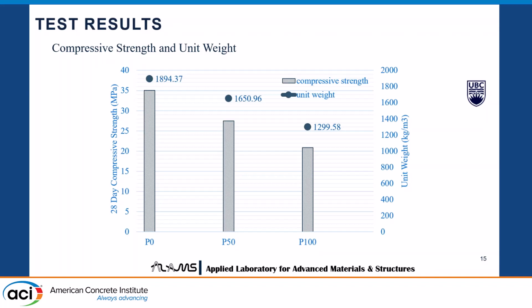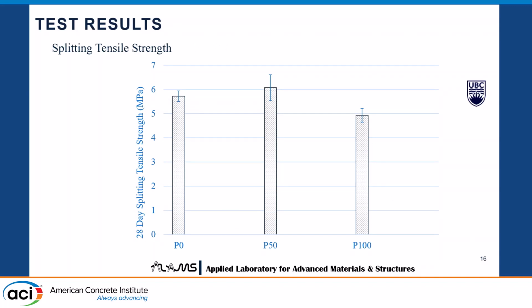But if we look at the unit weight, so the P0, it had a unit weight of around 1900 kg per meter cube. But the one with P100, as we can see in the third picture, it had a unit weight of only 1300 kg per meter cube. So we can see that the unit weight for the third one, P100, is more than 30% less than the control one. So we are making GFRC, so we want to make it lightweight as far as possible. So with 100% poraver, we can reduce the weight more than 30%. So this is the result of the compressive strength and unit weight.